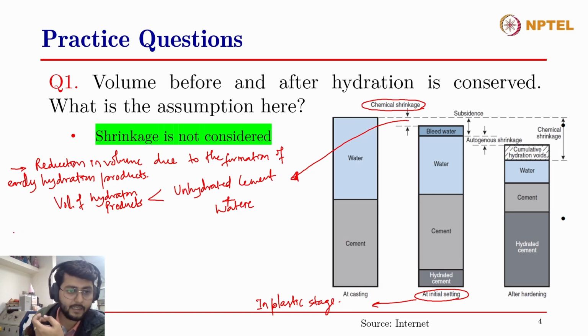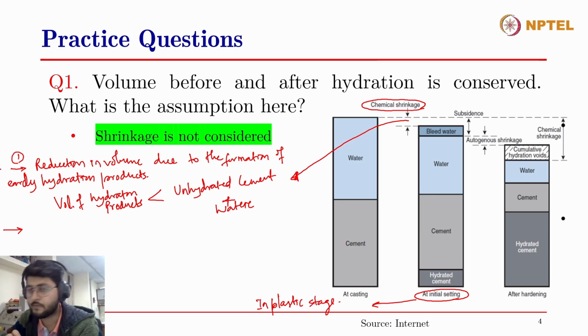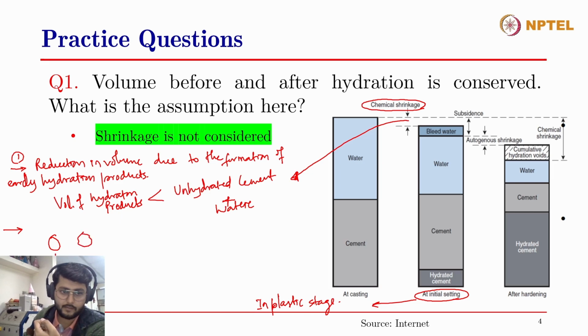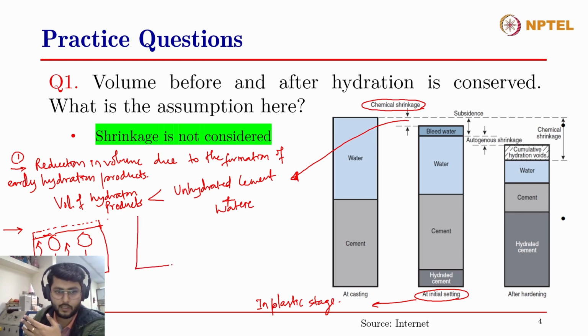Now there could be bleeding. This is for the first type of shrinkage, the chemical shrinkage. Then there could be bleeding in the mix as well. Let's say there is segregation in the mix. Segregation is the settling down of the heavier particles while the lighter matter comes on the top. So your aggregates are trying to settle down, and the bleed water gets accumulated on the top, forming a film. And when this film is formed, initially the volume was this much.